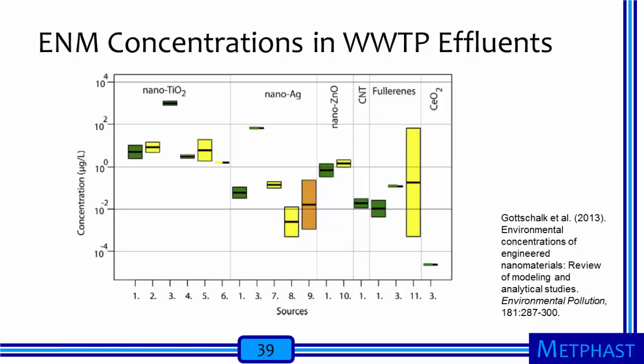With the exception of one study that estimated nanotitanium dioxide at concentrations of about 1 milligram per liter in wastewater treatment plant effluents, other estimates and several sets of measurements suggest concentrations of approximately 10 micrograms per liter. Concentration estimates and measurements for nanosilver, nanozinc oxide, carbon nanotubes, fullerenes, and cerium oxide nanoparticles are generally lower, with most concentrations in the vicinity of 1 microgram per liter or lower.